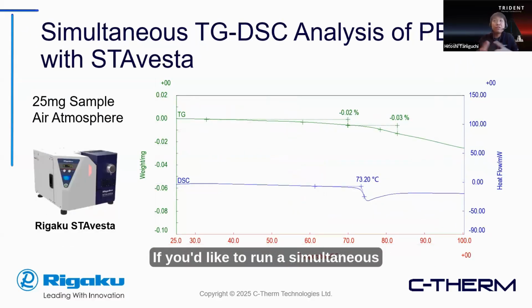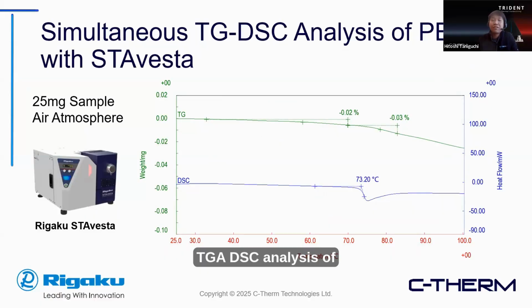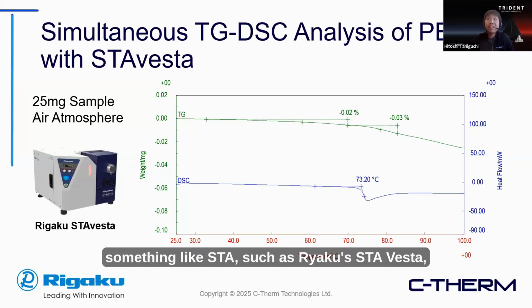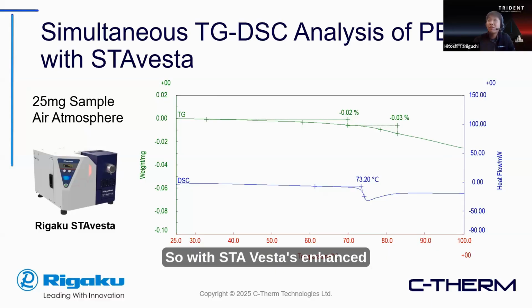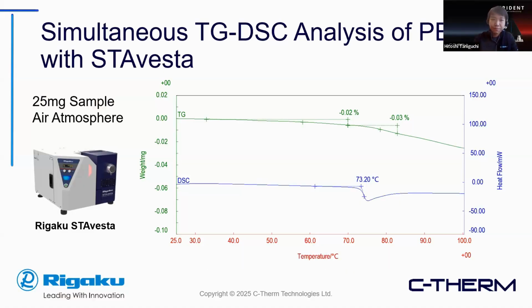If you'd like to run a simultaneous TGA-DSC analysis of your material, an STA such as Rigaku's STA Vesta is quite ideal for these kinds of applications. With STA Vesta's enhanced DSC sensitivity and TGA resolution, we can detect a glass transition of this PET material around 73 degrees Celsius with some mass loss. This is about 10 micrograms of mass loss, which is associated with volatilization and some trace gas off-gassing as the sample is being heated to 100 degrees Celsius.